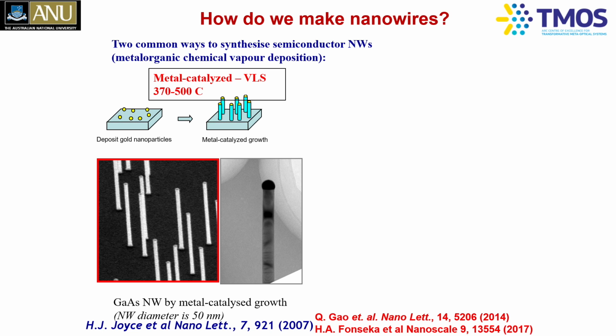And it turns out that gold has a melting temperature of more than 1,000 degrees Celsius, but once you bring it in contact with gallium or aluminum or indium, the alloy melting temperature comes down to as small as 350 degrees Celsius. So if you put this on a gallium arsenide substrate, for example, and heat it up to somewhere between 370 to 500 degrees Celsius, you create this so-called gallium-gold eutectic liquid.